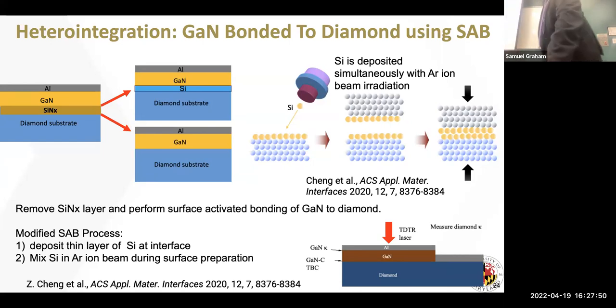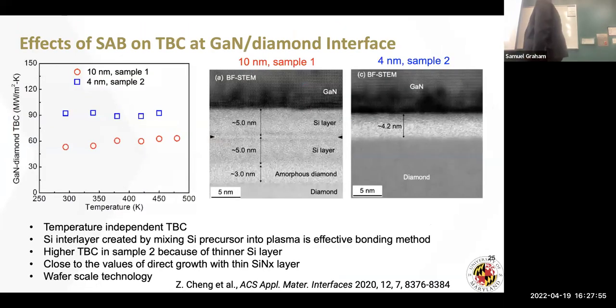And so these are just some tricks that we had to do to make this glue layer. What you see here is, again, 4.2 nanometer thickness. This is actually a layer of the amorphous material, as well as about 2 nanometers of this silicon-rich layer in the middle. So we get down to about 4 nanometers or so inside of this process. And what we have found is that this thermal conductance is as good as the best that we have measured in terms of thermal boundary conductance across GaN bonded to diamond.